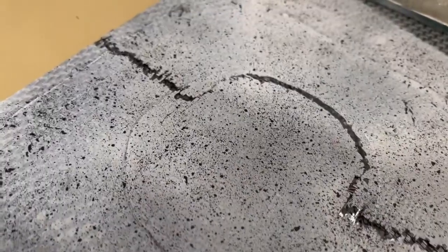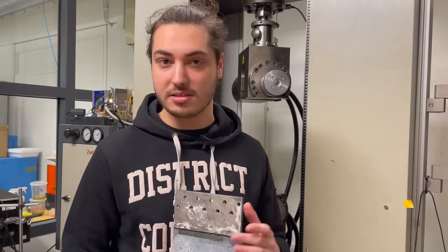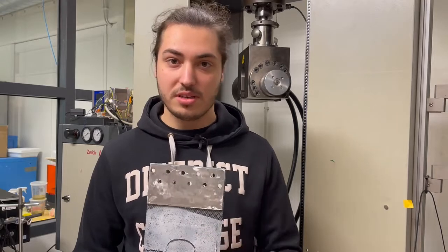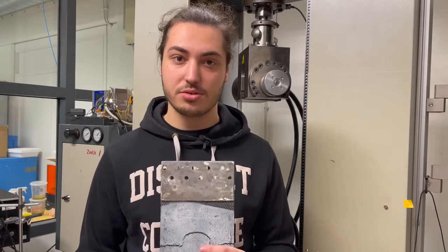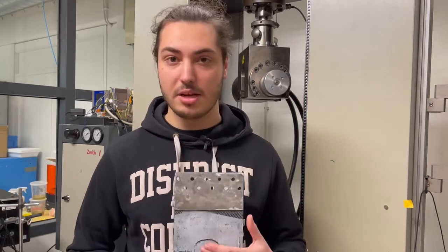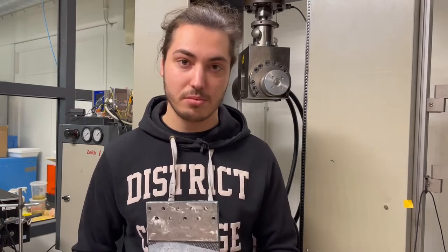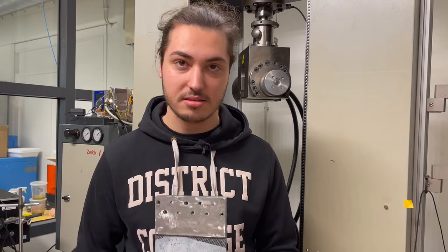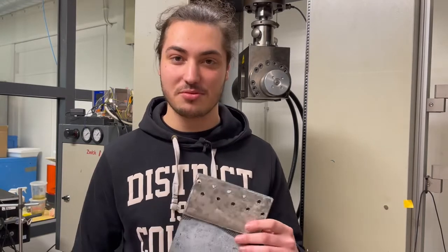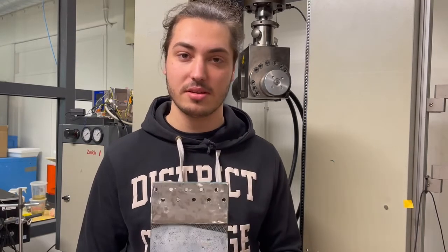The vision is that you could actually repair a thermoplastic laminate by using, for example, press forming in order to cure the patches. And I would say that the main challenge for the thermoplastic repair is the application of heat, because it requires really high temperatures. As you can see, this laminate has been cured using the press forming machine, which cannot really be transported in an airplane. Other applications, such as hot bonders, can be used in order to cure the patches instantly. Yeah, it has to be tested afterwards in order to see how the performance of the laminate is.